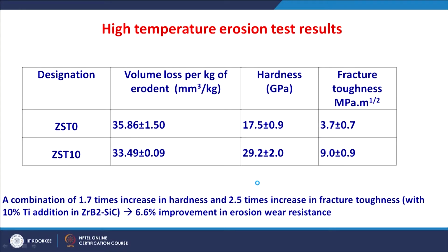The results from the high temperature erosion test: the material removed is measured by weight loss and converted into volume loss, and then converted into volume loss per kilogram of erodent, which we call the erosion rate.